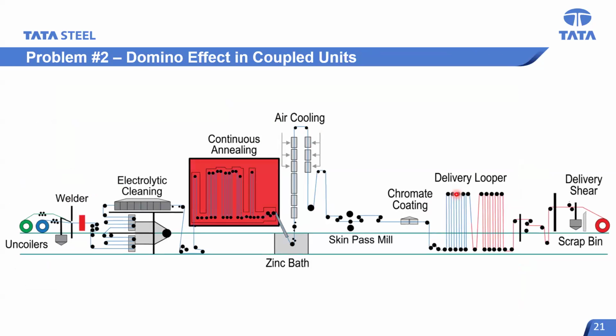So this is the other problem. Suppose there was some problem in the welder. The welding, which is supposed to finish in, say, 30 seconds, took slightly higher time, 45 seconds or 50 seconds. Soon that impact will be felt in the furnace, because we have to stop the line while welding is happening. The coil in the furnace will get overheated.